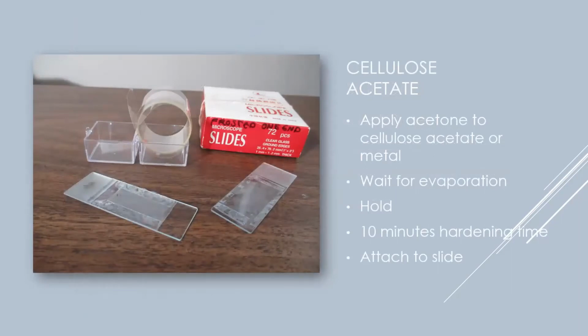You can see that roll there of film. You can get it also in a sheet. You wet it with acetone, apply it to the surface that you just got finished polishing and etching. You let it dry for about 10 minutes. You strip it off and put it on these glass slides. And of course, there's kind of a picture frame around the cellulose acetate to hold it flat.